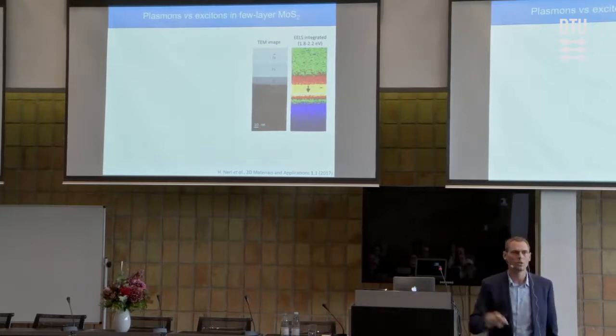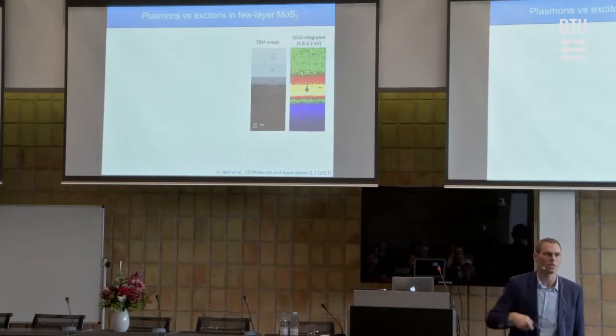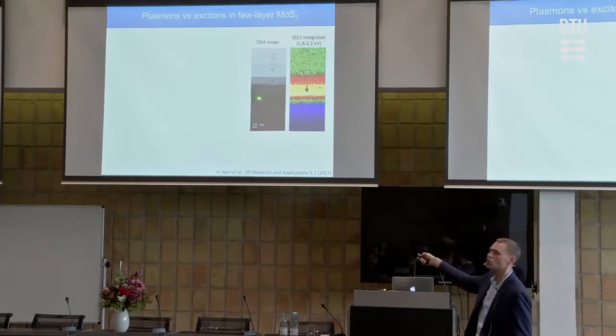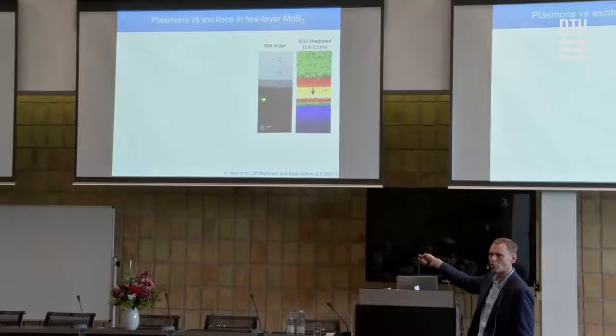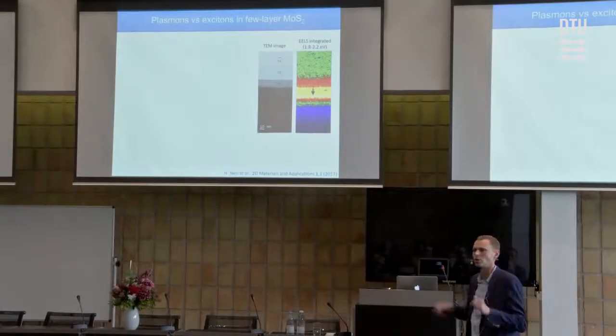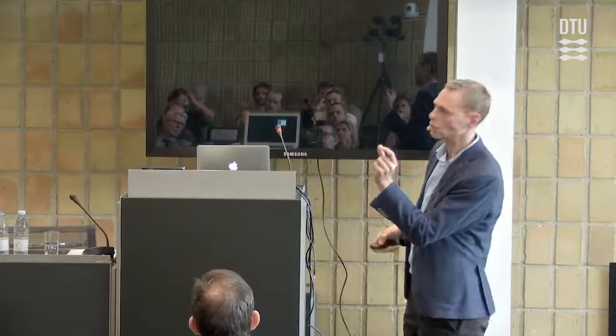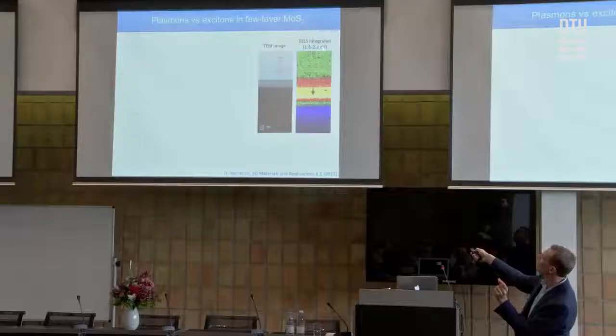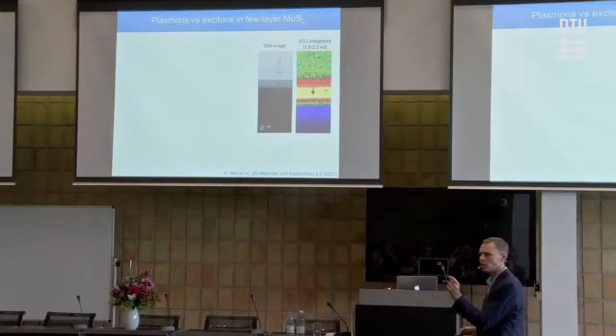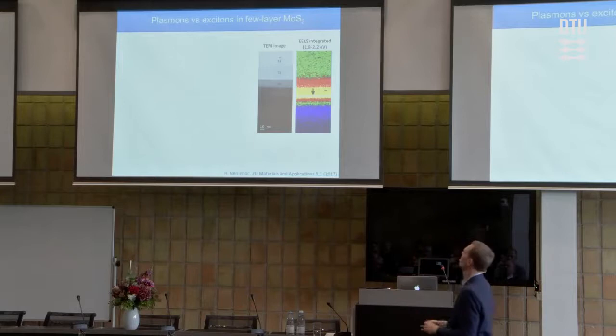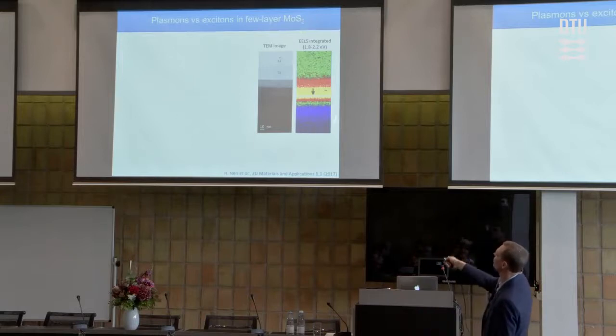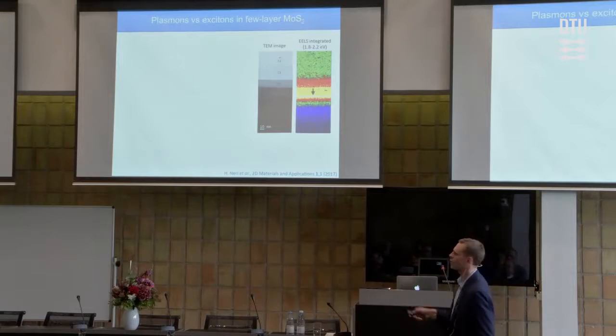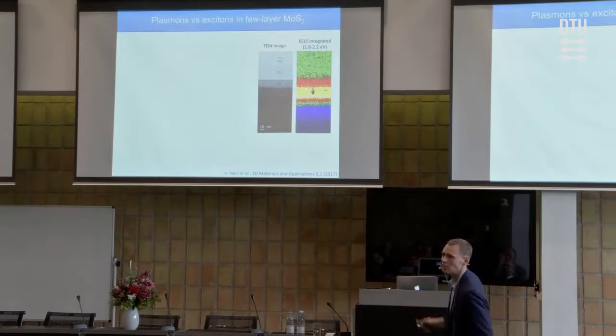So this means you take the electron beam, place it at a particular point over the sample, and measure the energy loss at that point to get a spectrum as a function of energy. You can integrate that energy spectrum over the area where the excitons sit, and produce a spatial map of that energy loss.